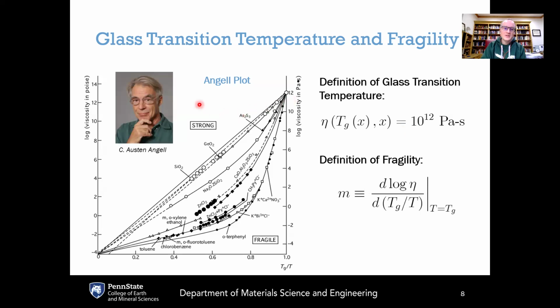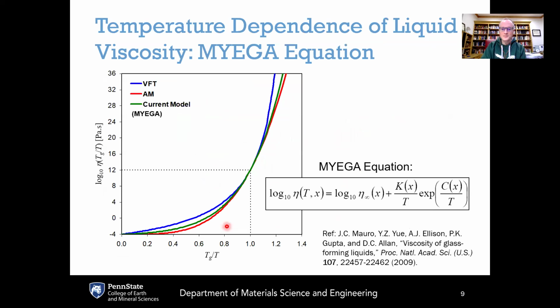And one of the nice things about the Angell plot is that if you know these two quantities, if you know the glass transition temperature and you know the fragility index for a given composition, then that gives you a really good idea of the entire viscosity versus temperature curve, at least for the liquid and the supercooled liquid state.